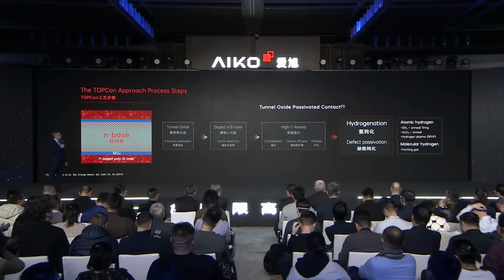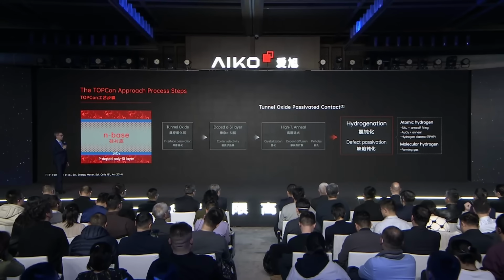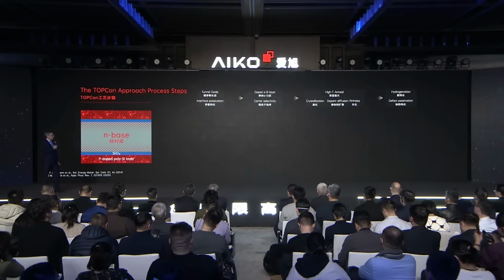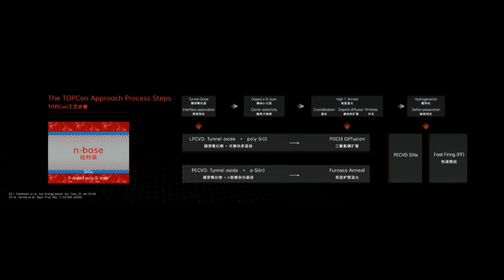And here it proved to be very effective to use atomic hydrogen instead of molecular hydrogen. And the industrial process sequence, I mentioned it before. On the one hand side, we have the LPCVD process, where we typically deposit undoped polysilicon onto the tunnel oxide, and then we dope the material by POCl3 diffusion, or we go the other way with PECVD, where we deposit phosphorus-doped amorphous silicon onto the tunnel oxide, and then we crystallize the structure by the furnace anneal. And for the hydrogenation, we deposit a dielectric layer like silicon nitride via PECVD, and then in the fast firing process, hydrogen is released from the layer and effectively passivates defects.